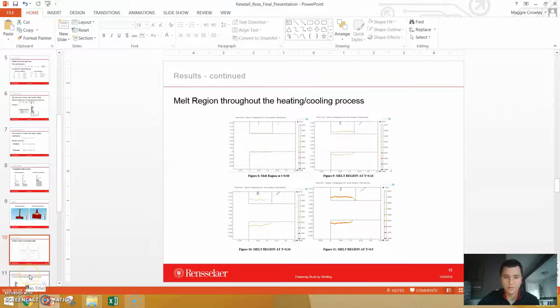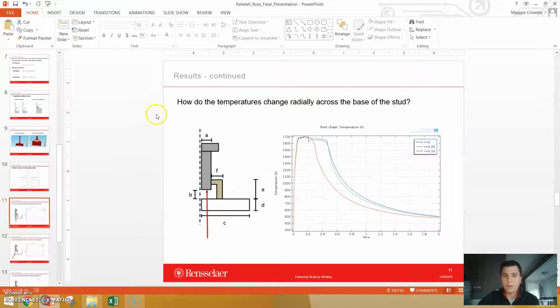So I looked into this a little bit further. I wanted to say, how do the temperatures change radially across the base of the stud? So if you look just at the base of the stud, I took 3 points. One at R equals 0, one at 0.05, which is about halfway, and one at 0.1, which is just before the edge of the stud. And you can see that these things heat up during the initial arc phase, and there's some melting occurring. And then once it's released, these things start to cool down.